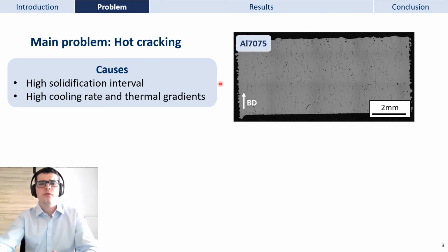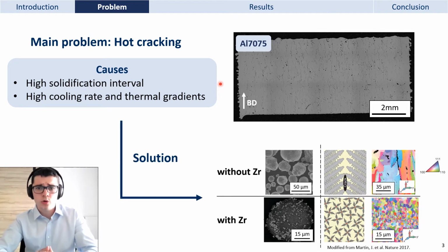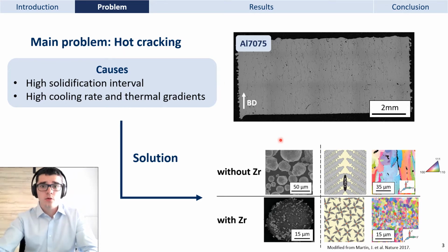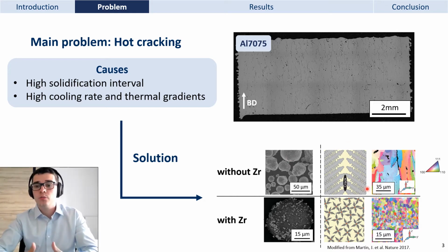But how to avoid these cracks? Martin and co-workers have shown that one solution is to add zirconium to the initial powder. When a classical powder is used, the dendrites grow in a columnar way, forming a microstructure composed of large elongated grains highly susceptible to hot cracking.